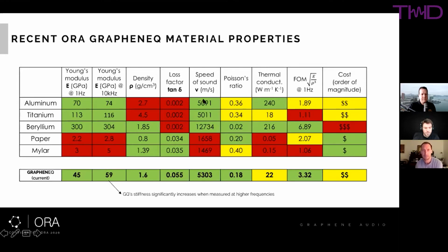And the speed of sound is based on the Young's modulus and the density. So the speed of sound in our material is actually currently faster than in aluminum, despite the fact that our material is a little less stiff. That's because of the much lower density that we have. We're almost half as heavy as aluminum, and so the overall speed of sound is a bit faster. So when we look at how our membranes work in the frequency domain, we're actually getting larger bandwidth than you might from an equivalent aluminum membrane.